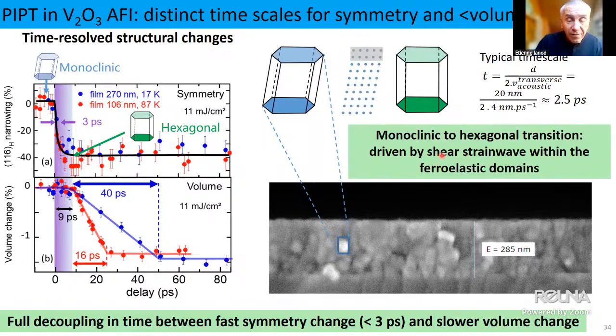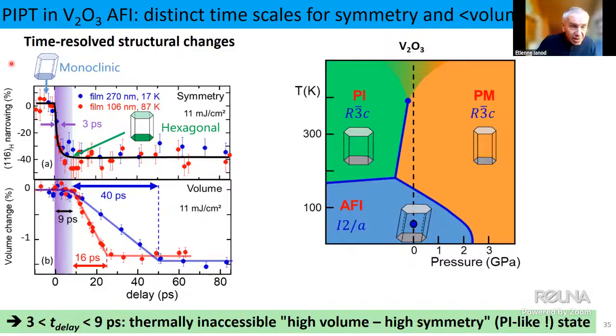So, in fact, we have some kind of evidence that the monoclinic to hexagonal transition is driven by a shear strain wave within the ferroelastic domains. What you might notice now, if I switch from the symmetry breaking part to the evolution of volume part, is that the volume has a waiting time of 9 picoseconds. To be honest, we don't know yet. We do not have a complete explanation of this, but what is quite funny is that between 3 and 9 picoseconds, the system still has a large volume corresponding to the insulating phase.